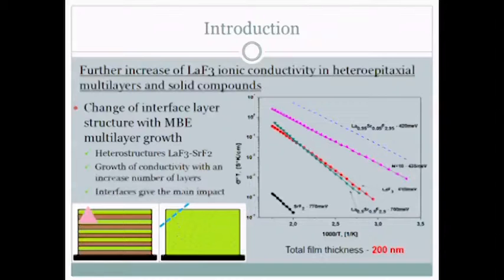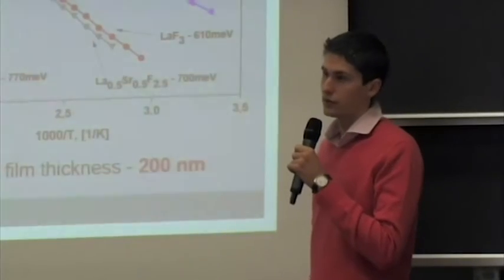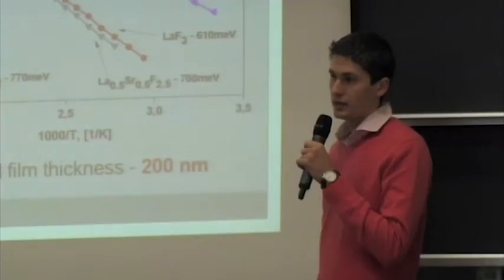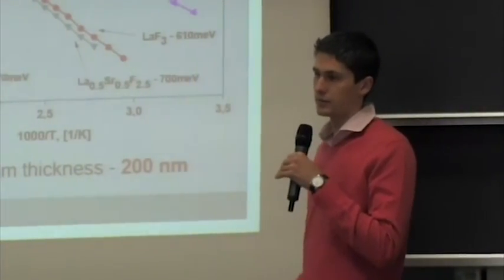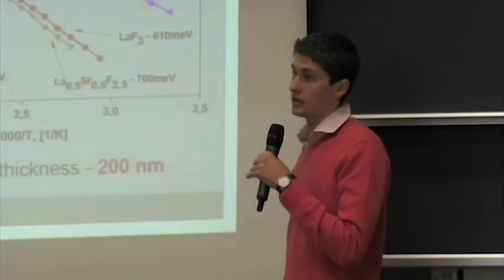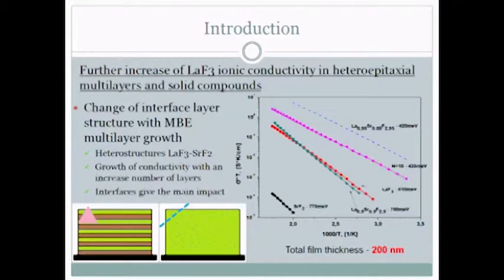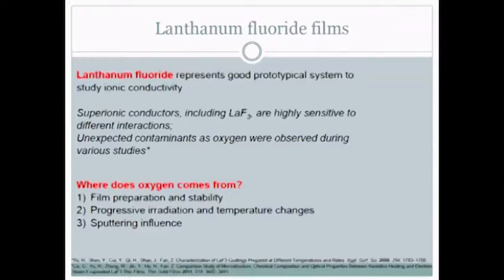To increase the conductivity of the material, it could be done in different ways. One of them is to create a multi-layer system, as you can see here. We've used a lanthanum fluoride, strontium fluoride multi-layer, and as you could see here on the graph, it's clean strontium fluoride or clean lanthanum fluoride conductivity, but if we use a multi-layer structure, it gives us 2 orders of increase of ionic conductivity, which is mainly related to the increase of interface layers, and this interface region has a different structure. This actually gives us this increase. And lanthanum fluoride is a good prototypical system to study ionic conductivity because of its relatively simple hexagonal lattice structure and relatively high ionic conductivity values.